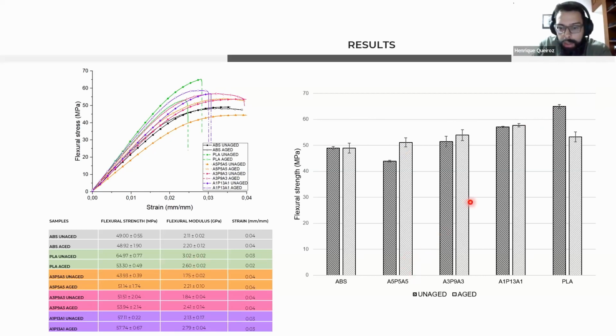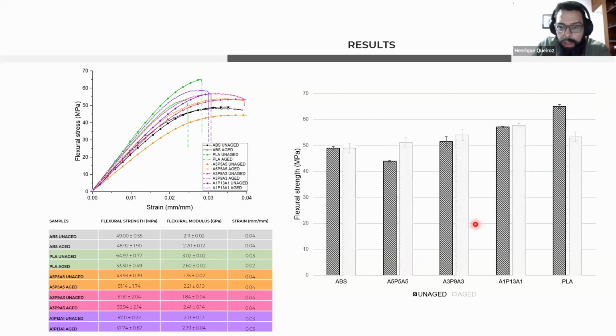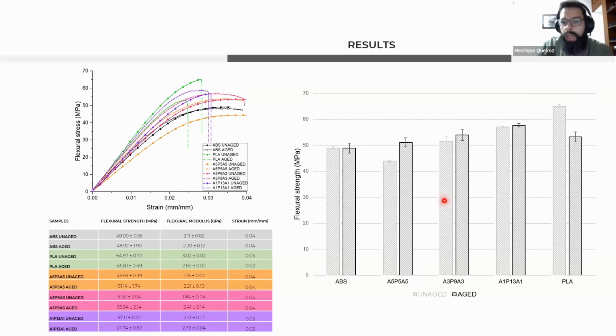And when we look at the aged, oh sorry, over here, at the aged specimens, we actually have a generalized plateau. This variation between, for example, this case and this is actually within 10%. So you could technically call this a statistical plateau. It didn't matter much for the aged specimens, which is very interesting because you would think that you would have more damage in one PLA one ABS compared to the other, but they all aged right about the same.